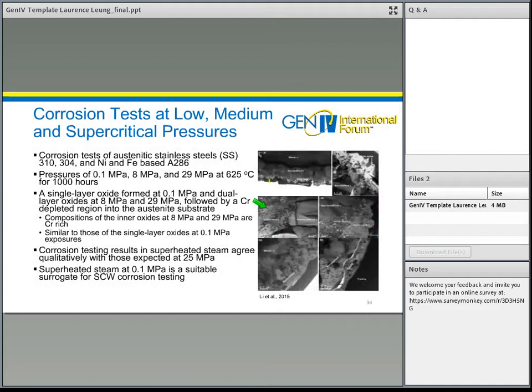So I mentioned that corrosion testing at high temperature is one of the issues. And we are also looking to find out whether we can use low pressure superheated steam as a surrogate condition to test at high temperature, high pressure. So they performed some corrosion tests on austenitic stainless steels 310 and 304, and the nickel-iron base alloy A286. They performed the tests at 0.1 megapascal, 8 megapascal, and 29 megapascal at 625 degrees Celsius for 1,000 hours.